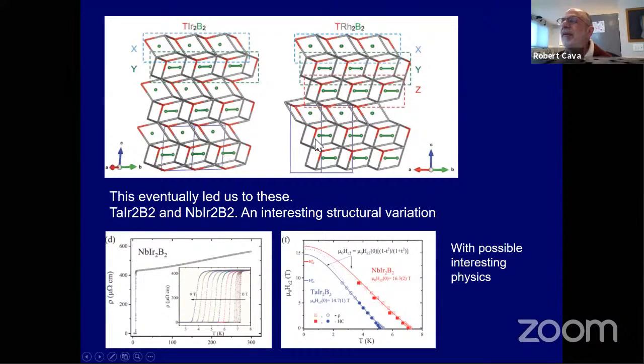And so once you can separate it that way, a basic principle of solid state chemistry is if you can identify building blocks, maybe you can put them together in a different way. So here is 2 and 1 and 2 and 1, and here is 1 and 1 and 1 and 1 and 1 and 1. And this is tantalum iridium 2b2. This is tantalum rhodium 2b2. These are also non-centrosymmetric chiral superconductors, and they have some